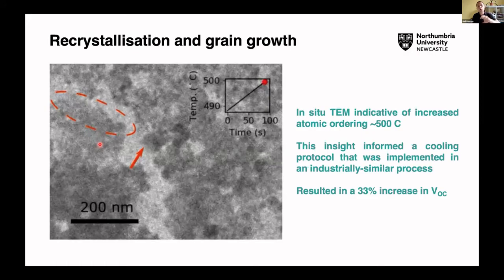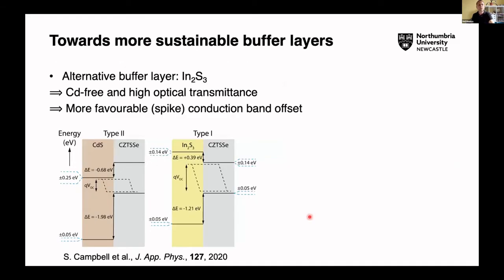And what we were able to do was transfer that protocol that we determined from the TEM to an industrially similar process, not an industrial process, but a macroscopic process. And we're able to use the insights to increase our VOC in the device by around a third, which was great. So really a good crossing of scales there, from the nanometer scale to the device scale.